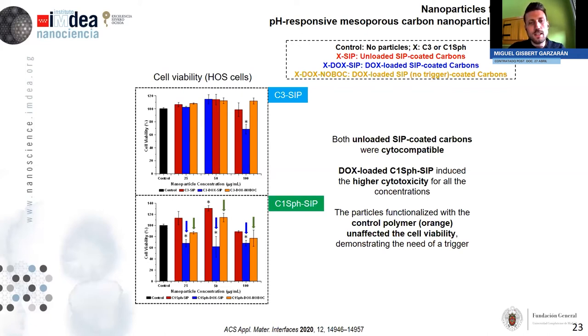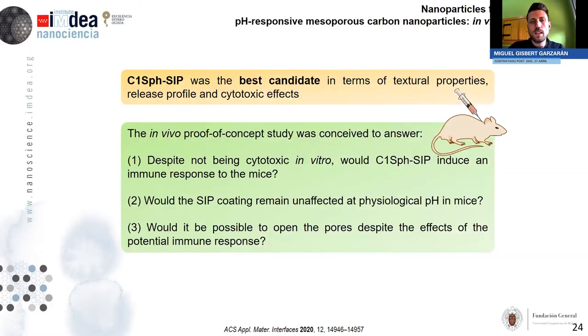As you can observe in the graph, it is clear that only in the case where there was the pH-responsive trigger, we could observe a decrease in the viability of the cells. So we can conclude that if there is a trigger, there will be release and there will be cell death. But in the opposite case, if there is no trigger, there won't be release, so cells will stay alive. Okay, so taking into account everything that I have shown, we could conclude that the C1sph-SIP nanoparticles were the best candidate because they had the best textural properties. They showed the best release profile, and they showed the greatest cytotoxic effects.